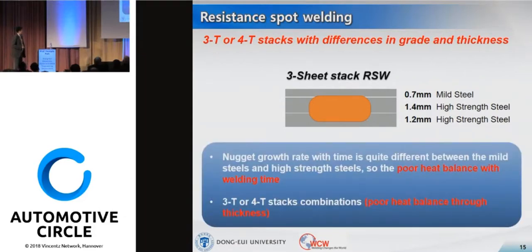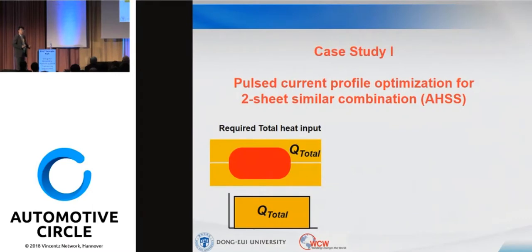However, in here, I'd like to emphasize one more thing. The nugget growth rate with time is quite different between the mild steel and high-strength steel. So there is poor heat balance with welding time in high-strength steels. And also, in case of a three-sheet and four-sheet stack combination, poor heat balance through the thickness. So what we have now in the actual field manufacturing line is poor heat balance with welding time and poor heat balance through the thickness. So how can we improve our welding quality or change this condition by using pulsed current profiles in here?